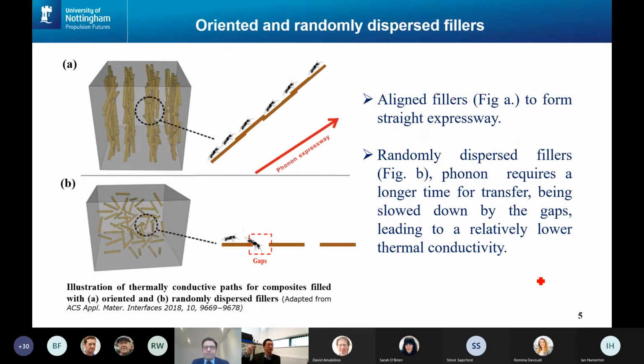Once the filler is added in the material, it really depends on the distribution and how the different fillers connect. If we need high thermal conductivity, first we really need the fillers themselves to connect with each other, like a bridge. So we can have this kind of phonon transfer much smoother and more directly, rather than having a gap like this one. And secondly, whether we need alignment of the filler or randomly distributed filler inside the material.